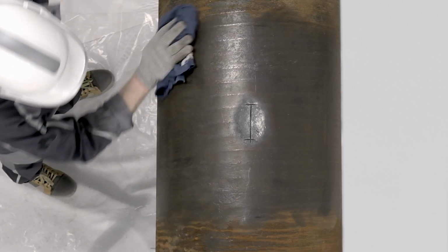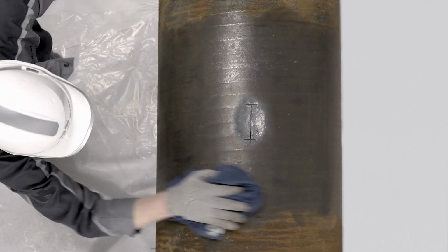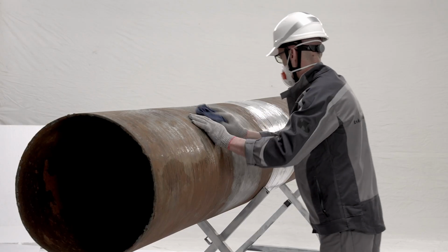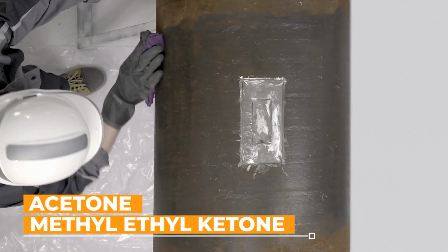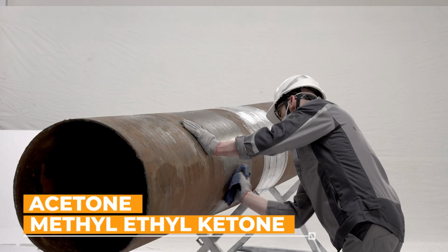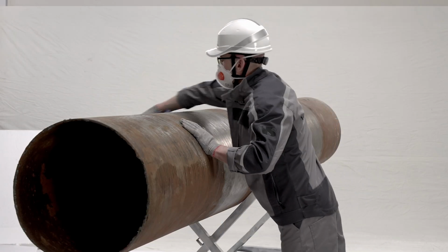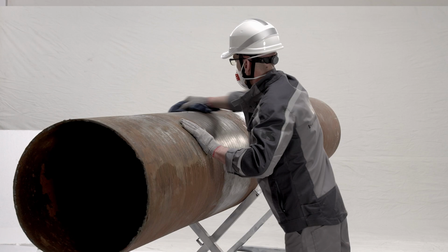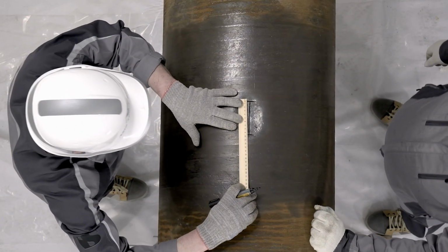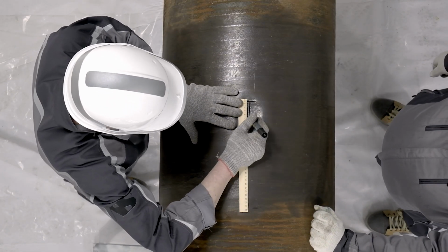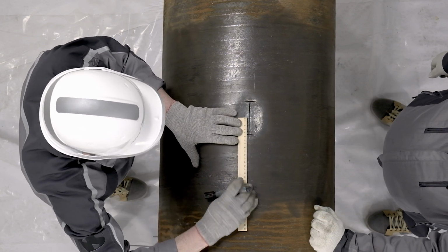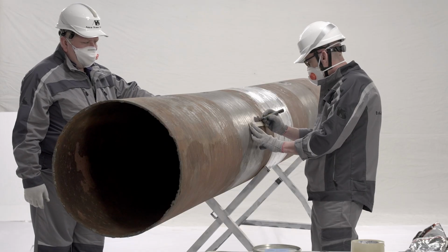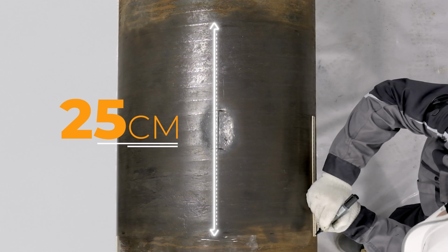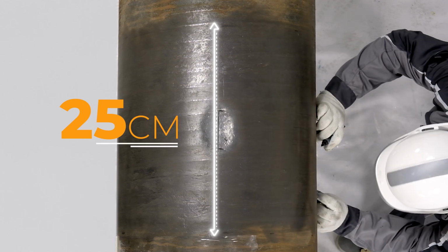In the places where the coupling is installed, the surface of the pipe should be wiped with a cotton rag and degreased with acetone or methyl ethyl ketone. The use of gasoline to degrease the pipe surface is not allowed. The defect should be located in the center of the area to be repaired. Mark the area to be repaired on the pipe. Make sure that the mark extends beyond the center of the defect at least 250 millimeters.